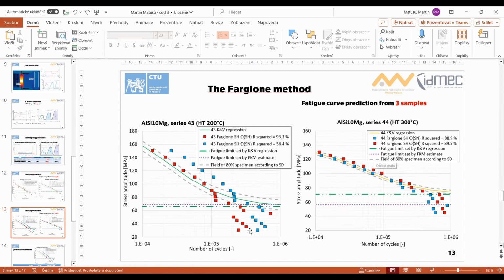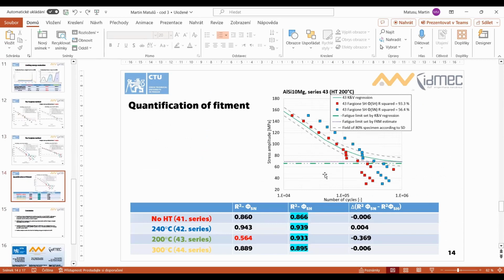For the T300 series, there is a good correlation of both, although I would like to say that the standard deviation for K&V regression was so good that even the red points are outside of the field. Yeah, so this is only the coefficient of determination, and I'm already too long. I would like to point out that for the limiting energy from the self-heating step test, the coefficient of determination is quite good. We come up to quite good results.